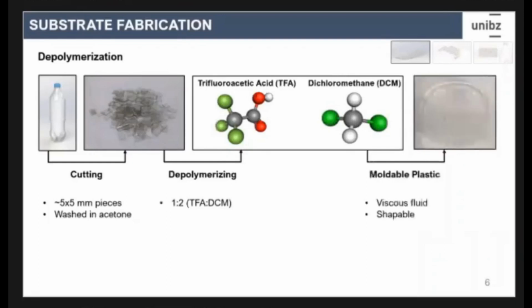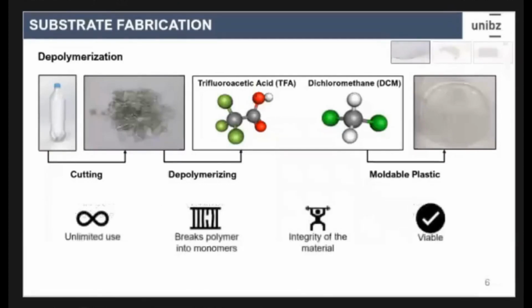Basically, the depolymerization consists in taking the long polymer chains and creating monomers out of them. In the end, we end up with a translucent and viscous liquid that is shapeable and moldable, and it remains liquid during the depolymerization stage for a very long time. The advantage, again, is that in theory we're creating virgin plastic with it, so properties are not lost.